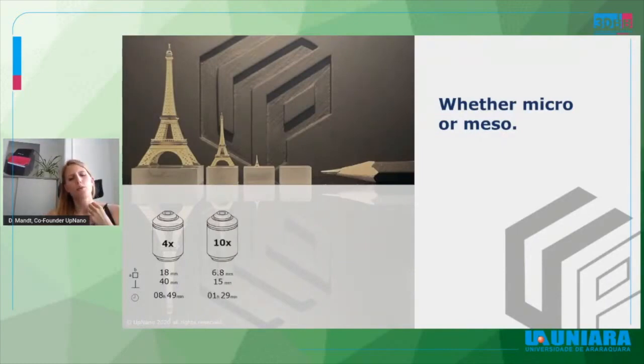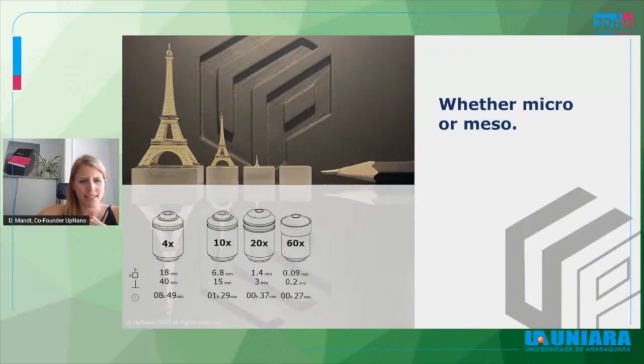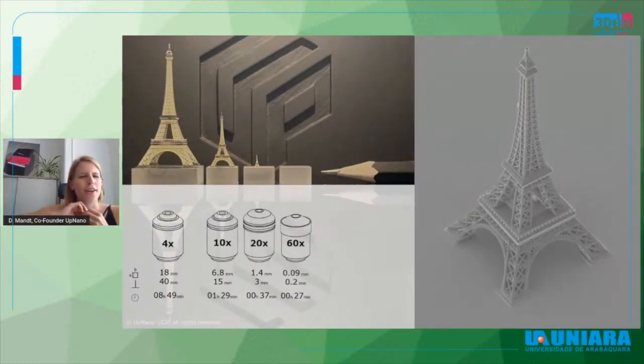Going down the scale, with the 10x objective, you can print smaller structures, still the same features, just on a smaller scale. And this image should just give you a visualization of what is possible with the different objectives. So when going down the scale, the magnification is increasing and the size of the objects we are printing is basically decreasing. And last but not least, we have the 60x objective. And here we printed a 0.2 millimeter in height Eiffel Tower, so a 200 micrometer height Eiffel Tower, which can't be seen anymore on a normal photo, but which can be seen on a scanning electron microscope image. And here again, all the small details and the fine features are perfectly fabricated.